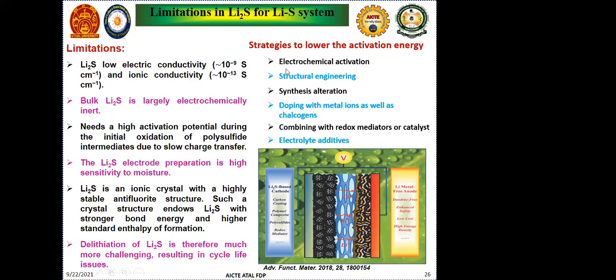So when we think of strategies to recover from all these issues, we can go for electrochemical activation of Li2S. Especially this is done by changing bulk Li2S to nanomaterials. When we make it nanoscale, then Li2S becomes conductive. And we can also focus on structural engineering and synthesis alteration. When we synthesize Li2S by different processes, then the conductivity also increases, or it becomes more electrochemically active.